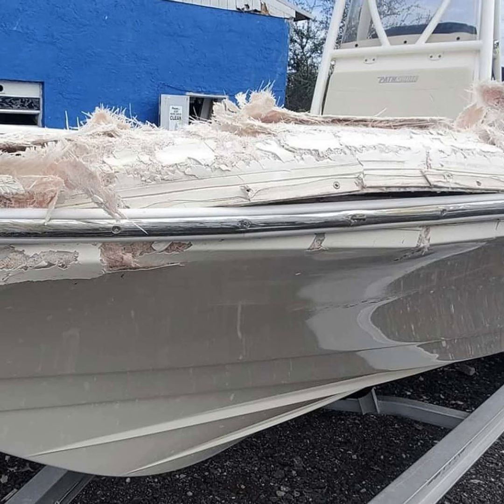Yeah, exactly. And basically what that is showing you is that at some point, the fiberglass flexed beyond the limitations of the gel coat's ability to flex with it. And maybe the fiberglass took damage underneath the gel coat as well, or maybe it didn't. But typically, fiberglass is a lot more flexible than gel coat, which is essentially not flexible at all. So you can have circumstances where the fiberglass flexed beyond the gel coat's range, but the fiberglass didn't fail. Or you could have circumstances where the fiberglass flexed beyond the gel coat's range and the fiberglass failed.